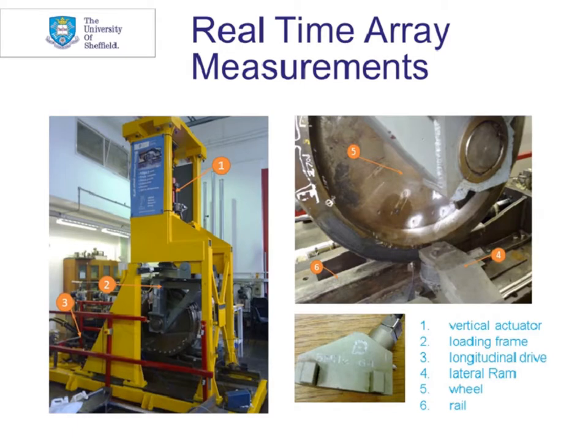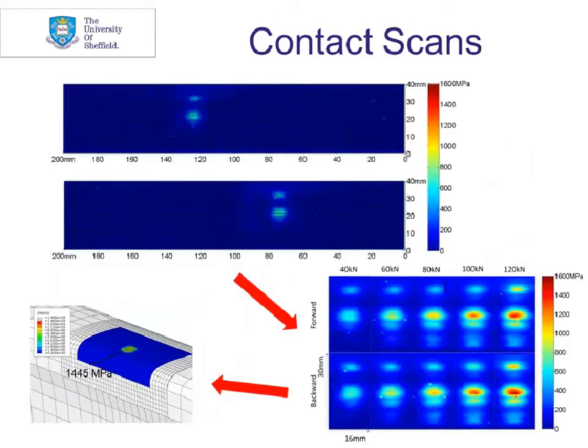Within this rig, we're loading an actual train wheel against the length of rail, as you can see in the picture there. The rail's then pulled underneath the wheel, and we can apply different levels of slip and realistic normal loading conditions. Now, obviously, we're taking these contact scans at a much higher speed, so we lose a little bit in terms of resolution, but you can see here we're capturing a nice image of the contact, which we've now validated through some finite element analysis, as you can see in the image in the bottom left-hand corner. Of course, this step is great, but not many people are going to allow us to cut a hole in the rail for us to insert an array. So we needed to find a slightly different way to take this measurement technique into the field.